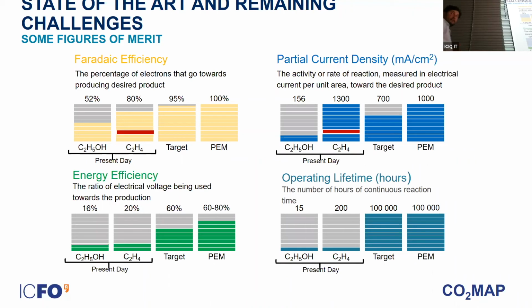The energy efficiency, in any case, is still low. For both cases, the energy efficiency at the system level, at the electrolyzer level, is around 20%, whereas the ideal target for a viable operation is still far. It's still 60%. There are still lots of things to do on the cathodic side to improve CO2 reduction, but there are also other things to do on the anodic side. If you remember the picture when I was showing you the electrolyzer, I mentioned that water is split and is oxidized to generate oxygen. But oxygen has little to no value, at least in this world, unless you were on Mars, for example. So why not use another kind of oxidative reaction that could add value?